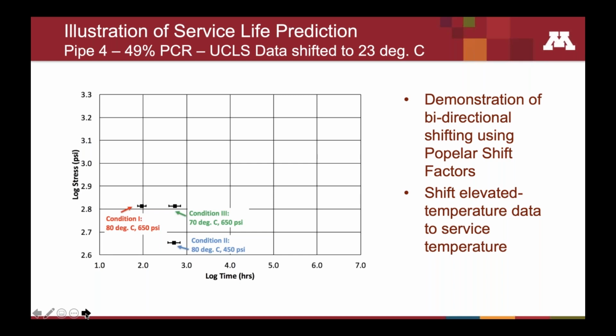The next thing we do is we apply those shift factors, the Popelar shift factors, a vertical shift factor and a horizontal shift factor. And those shift factors are simply functions of the temperature difference from your desired service temperature and your test temperature. And by doing those shift factors, we can then map a data point, shift that data point, if you will, to some service temperature. 23 degrees C is a fairly conservative assumption for the temperature of a pipe in a buried application, say in a state like Florida or one of the southern climates.